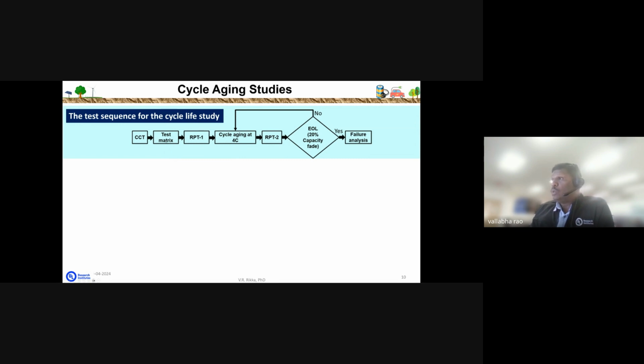And then once you define the test matrix, we will carry out the reference performance test, which helps us as a reference point for identifying what level of aging mechanism has occurred during the cycling conditions. And then after that we will go for the long continuous cycles until the cell reaches 80% of its initial capacity. Once it reaches 20% capacity fade, we can consider that cell as the end of life.